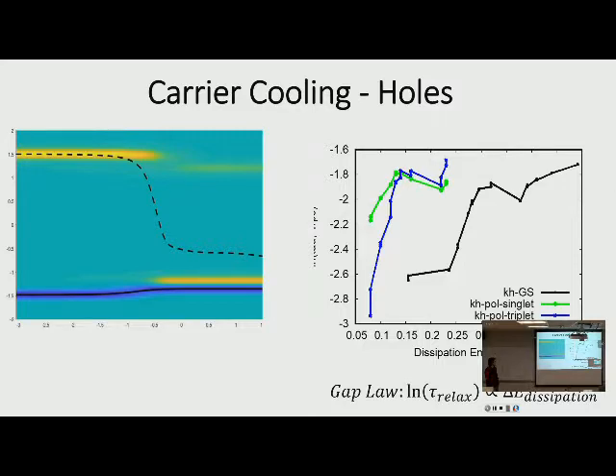Then I did do a comparison of hole cooling rates as a function of excitation energy for these systems. And so that's this spot here. The black line is if you excited the neutral state, or hole cooling in the neutral atom anyway. And then green and blue correspond to singlet and triplet for the polarons. The trends are pretty similar, but you can see that all of them have some region where it looks partially linear initially, as a dip, and then linearly increases again. So they all show that feature, but at different rates, where the triplet shows the fastest relaxation in these systems.